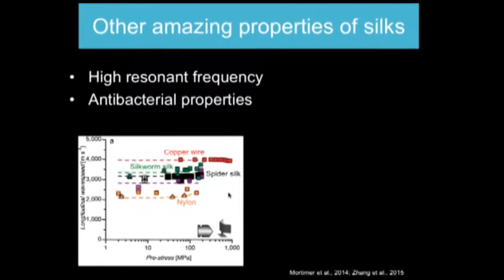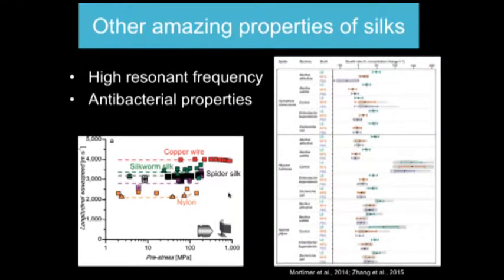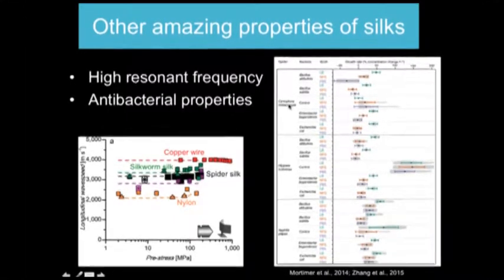They're compression waves. And this is dependent upon the resonant frequency. So you can see that it's very, very high, quite similar to copper wire or a metal, and much higher than nylon. And the reason this is significant is because many materials that are used in construction and building, such as tubing, need a high resonant frequency, because low resonant frequencies, which is where most ambient noise comes from, can cause destructive resonance, resonance that destroys the material when you use it. So having very high resonant frequencies is quite useful if we can capture those properties.